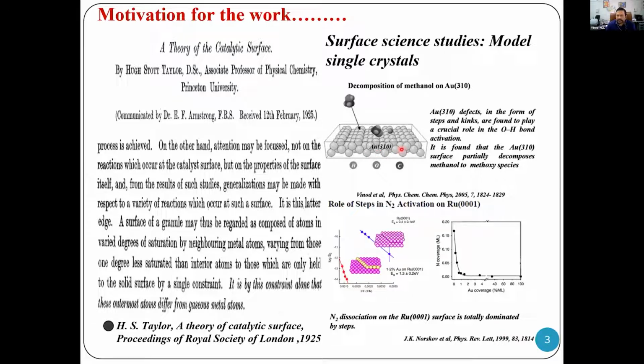We also did some work. This was basically trying to look at the activation of molecules on a gold surface. Gold is very interesting because in bulk form it is not active, and you have to really make very small particles to make it catalytically active. So what we found is that if you have a stepped single crystal surface of gold in the form of 310, then you can activate molecules like methanol or nitric oxide and so on.